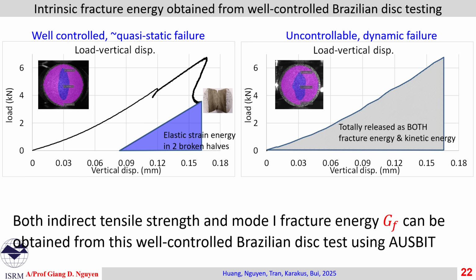So this works, and if we make a comparison, say with an uncontrollable test like the standard Brazilian test, we usually get this kind of energy dissipation, because at the peak, the specimen suddenly splits into two halves in a very violent way, and the energy released in this case includes kinetic energy, which we want to remove.